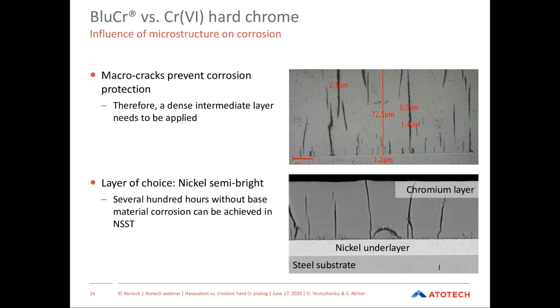So if you can see on the right side, a cross section again of a chromium layer deposited from blue chromium bath. You can see the micro cracks, but you can see also macro cracks, which go through to the substrate. This means that having these macro cracks will prevent corrosion protection, as in this case, for the corrosive media, you have a direct pathway to your substrate, steel. That means that very soon you will see the corrosion spot on your chromium, like red rust.